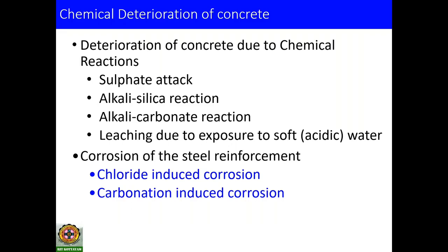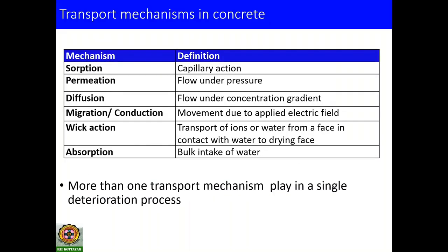In different ways we can categorize the deterioration of concrete as chemical deterioration, physical deterioration, and so forth. This is a compilation of the different chemical deterioration of concrete, and why especially the chemical deterioration is happening. We know that for sulfate attack to happen, it needs the presence of sulfate ions, SO4 ions. Not only that, water is required. For steel reinforcement corrosion to happen, it needs the presence of either chloride ions or carbon dioxide, along with oxygen and moisture. And for the alkali aggregate reaction to happen, it needs the presence of moisture.